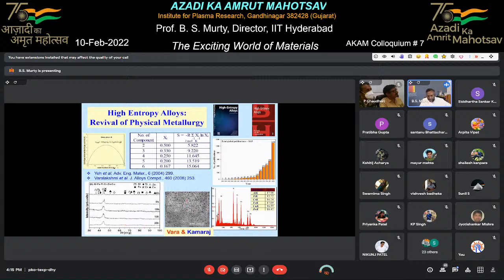And you take these particles, they are all nanoparticles, and put the electron beam on each of the particles. You can get the composition of the particle, and the composition of the particle is very close to what is called equiatomic composition. If you have 6 elements equal in proportion, each element should be 16.6, 100 divided by 6, and you can see this composition very close to that. Within 1 or 2%, it is very close to that. So it is possible to say very uniformly distributed elements in all these nanoparticles.